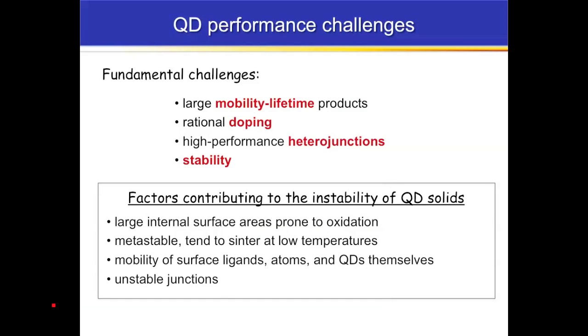What I want to touch on briefly is the stability issues related to using quantum dots, especially the lead salts, in devices. So I said before that we have a number of fundamental materials challenges. We need to worry about diffusion lengths. We need to worry about making better heterojunctions, but also stability is an inherent problem. Why is it such a problem? It's because quantum dots are high surface area and high surface energy objects. And so their high surface areas make them prone to oxidation, and this is particularly problematic in the lead salts, where oxidation leads to a big change in the electronic properties.